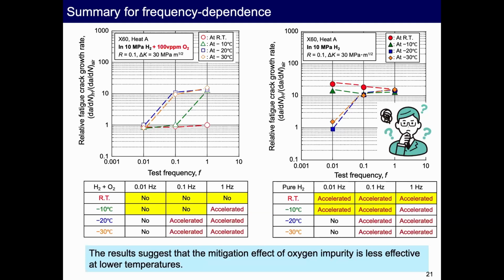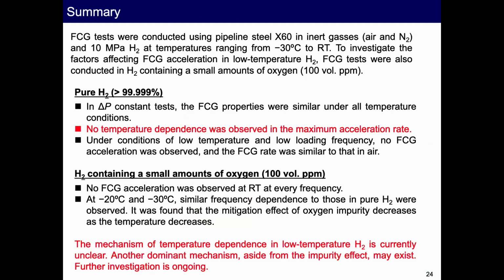Anyway, I have no clear answer to show you today, but I'm pursuing the mechanism and influencing factors. So this is the summary of my talk. I'd like to emphasize that no temperature dependence was observed in the maximum acceleration rate down to minus 30 degrees C. That's good news. But the mechanism of the temperature dependence in low temperature hydrogen is currently unclear. Probably another dominant mechanism aside from impurity effect may exist, but further investigation is ongoing.